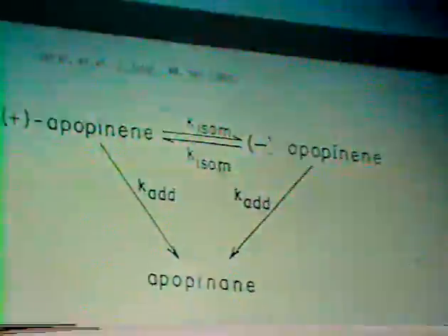Well, one of the things that we found was really, well, before I do that, I'll tell you a little bit about how we get information. Why is this molecule neat? Why is it so good? Because on a symmetrical surface, its double bond isomers should react at exactly the same rate. So if the surface is symmetrical and not asymmetric, then this molecule should go back and forth if the double bond can isomerize. But both of these should hydrogenate at exactly the same rate.